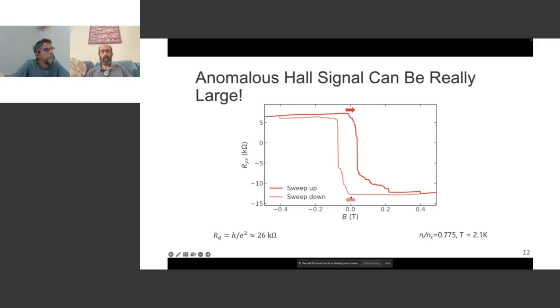The biggest Hall signal we see, it's not symmetric about zero, but it's about plus or minus 10 kiloohms. That's huge. And in fact, it's suggestive. It's getting on the order of the quantum of resistance, a resistance made up of universal constants of nature, h over e squared, which is about 26 kiloohms. Many of you may know that that's something that's seen in the quantum Hall effect. So this was really striking. And by the way, let me point out that this is at 2 Kelvin, so it wasn't actually colder than the other measurement, but it was in a better filtered cryostat, so the electrons were in a quieter electromagnetic environment.